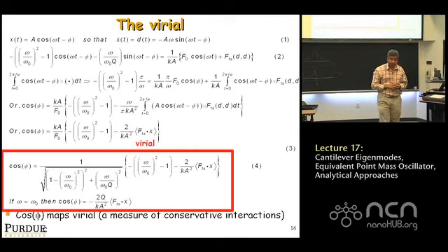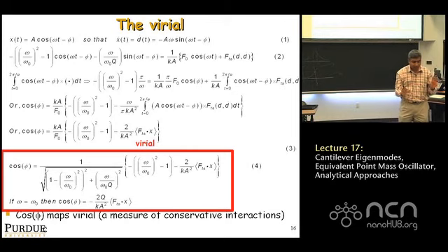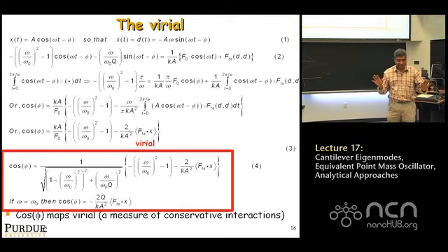Okay, this is a very spectacular, let's say the left hand or the evil cousin of phase contrast. The standard derivation you see is with respect to sine of phase, right? But you look at the cosine of phase, it's the twin. It's the evil twin, so to speak, that exists, and people don't know what to do and how to deal with this. Okay. What this means is, when you take a phase contrast image, you cannot just directly say, oh, this is dissipation.